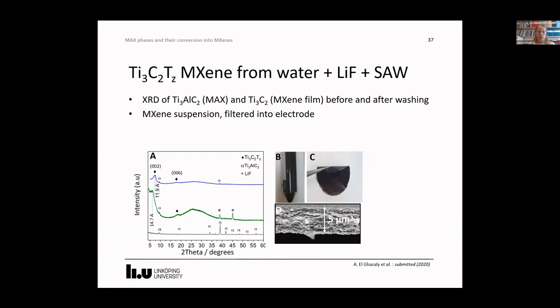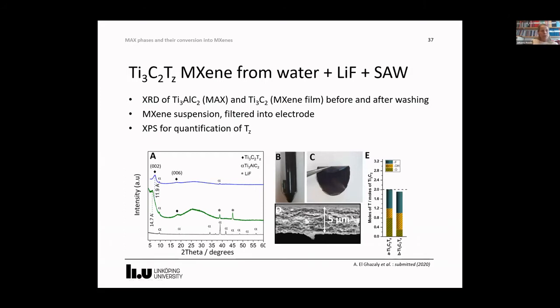Figure B therefore shows the MXene suspension after the one-step surface acoustic wave MXene synthesis and the resulting MXene electrode obtained after filtering. And here is also the cross-section. To evaluate and quantify the MXene surface terminations, we did XPS. The results show no aluminium as expected and a similar fluorine content compared to a traditional titanium MXene obtained from etching in lithium fluoride plus HCl.